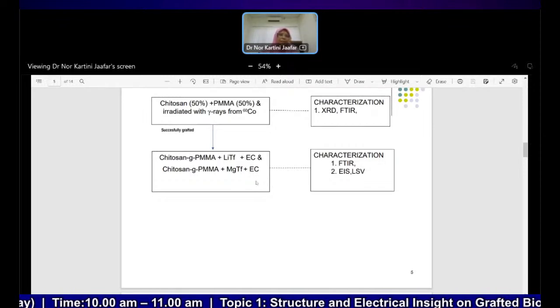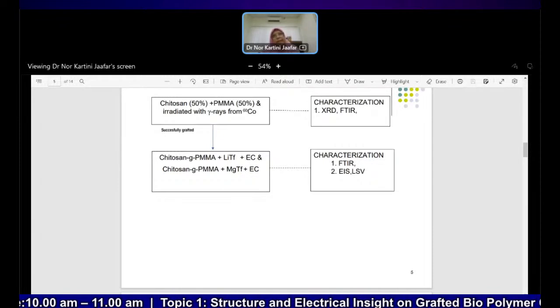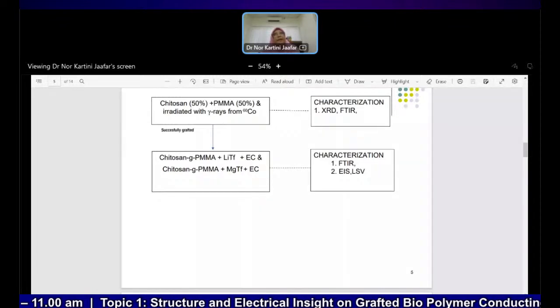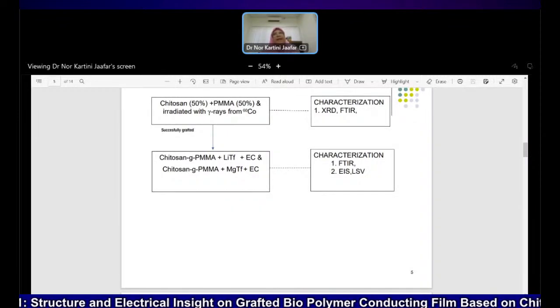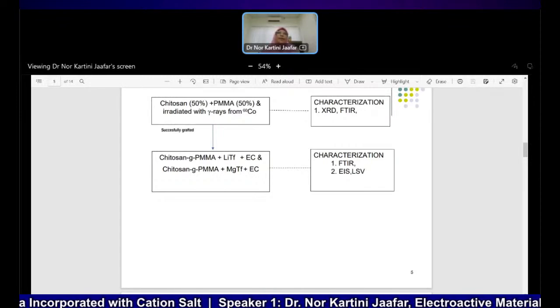There is a bit of a problem with lithium. We know lithium has very high solubility as a salt within the polymer, very active, and can produce very high conductivity. But the problem is that lithium itself is very active and cannot be exposed to air, or it will be destroyed. Any preparation of the electrolyte with lithium must be done in a glove box.